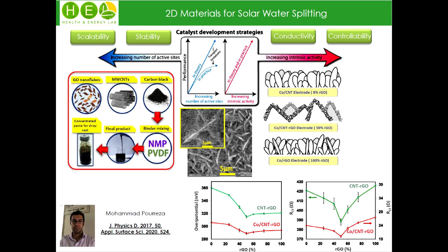First, we found that there is an optimum current density and deposition time for a galvanostatic approach in electrodeposition of layer-like or flake-like cobalt oxide. Fortunately, the surface was a mix of oxide and hydroxide phases, but the core was nearly metallic, so we had very good conductivity in the system.